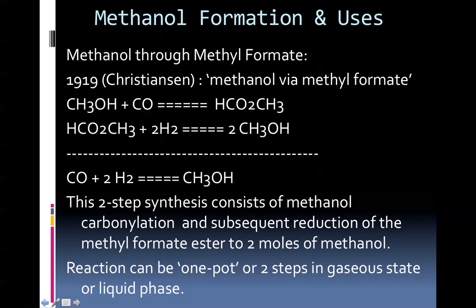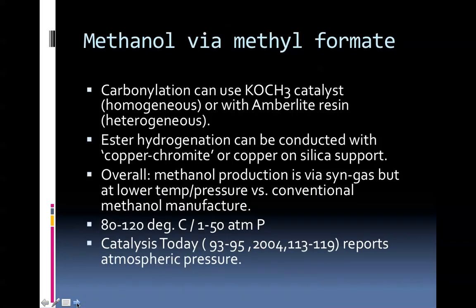This two-step synthesis consists of methanol carbonylation and subsequent reduction of the methyl formate ester to two moles of methanol. The reaction can be a one-pot process or two steps in gaseous state or liquid phase, either one. Carbonylation can use potassium methoxide catalyst, homogeneous, or with amberlite resin, which is heterogeneous. Ester hydrogenation can be conducted with copper chromite or copper on silica support.